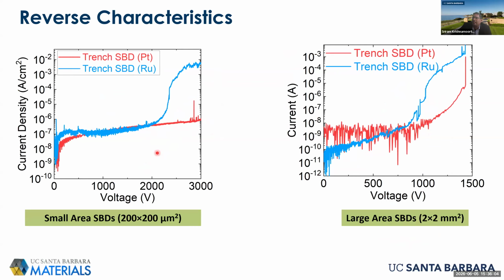And when we scale the area of these devices, the breakdown voltage does suffer, which means we do have some weak spots. When we scale the area, we still need to understand the microstructure and the leakage mechanisms, and maybe killer defects in the epitaxial layers and so on. So these are open questions. These are important questions to look at when we try to scale the area of the devices. But nevertheless, we can see that the reverse leakage current in these structures is extremely, extremely low.